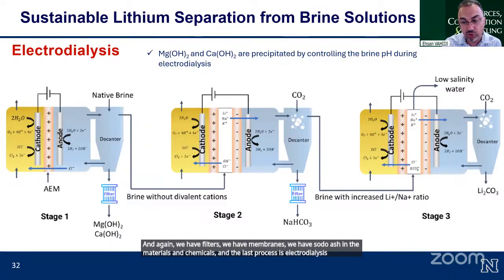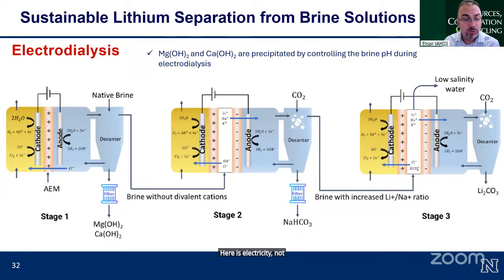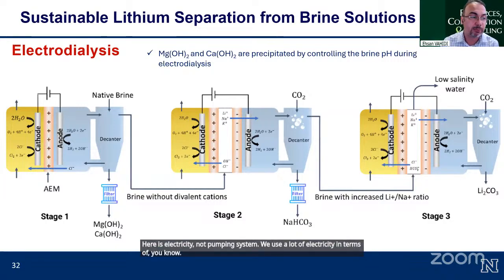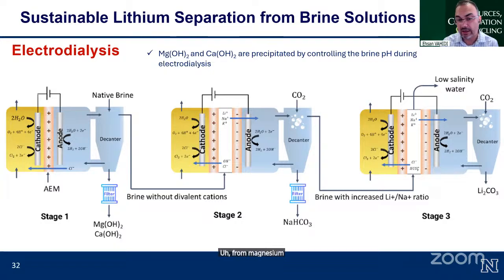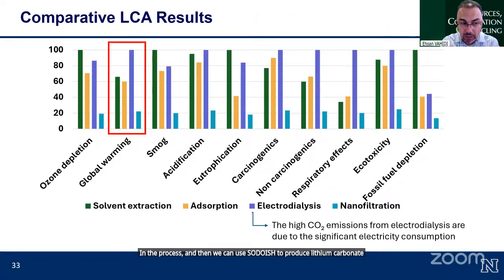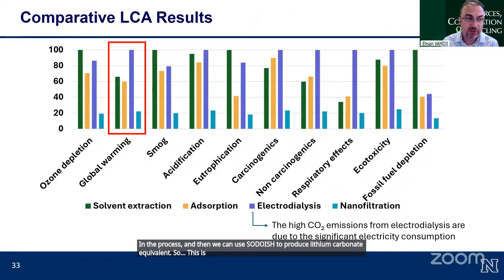Here it is a little bit different. The driving force here is electricity, not a pumping system. We use a lot of electricity as the driving force. We can separate divalent ions from monovalent ions, and then separate lithium from magnesium and calcium, and then we can increase the concentration of lithium in the process, and use soda ash to produce lithium carbonate equivalent. So this is what we have in terms of the comparison.